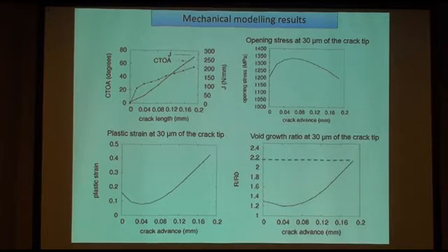So what are the results for this? If you extract the crack tip opening angle over the course of the crack propagation, you can extract also the J integral, and it's a constantly increasing value with rather high value, which means that it's not worrying for applications.